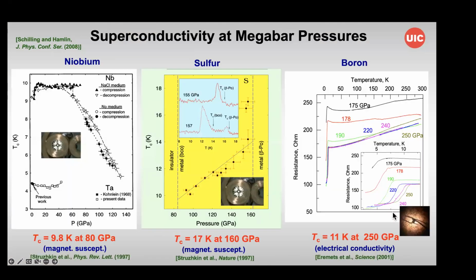The work that has been quite important experimentally for us in the hydrides is getting up into the megabar range. So an important breakthrough in the late 1990s was the first measurements on elements, superconductivity, TC measurements as a function of pressure up into the megabar pressure range. This is just an example of a few: niobium, sulfur, and boron, using magnetic susceptibility methods as well as electrical conductivity methods. Discovering these new superconductors or measuring high pressure properties, for example, of niobium, and looking at transitions such as Lifshitz transitions in these materials as detected by the variations in TC with increasing pressure.